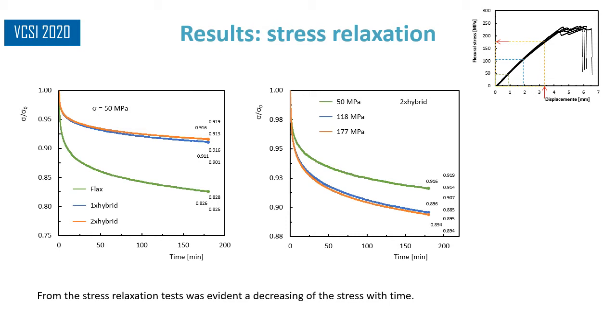In terms of stress relaxation, tests were also performed with the same equipment at room temperature and with geometry similar to those used for the bending tests. All experimental procedures were supported by standard tests. A fixed strain is applied and the stress is recorded as a function of time. The strain values used in the different laminates were